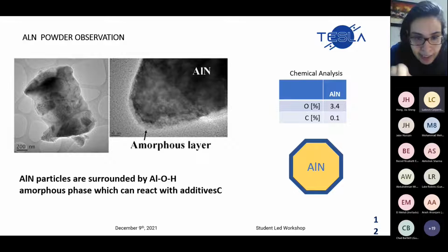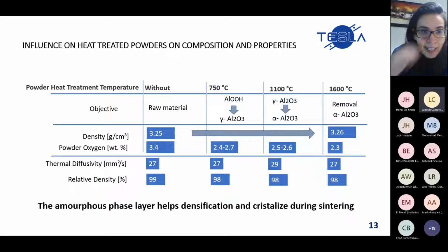Take into account this amorphous layer. We did some thermal treatments to change the chemical structure of the secondary phases. So the amorphous layer helps the sintering.